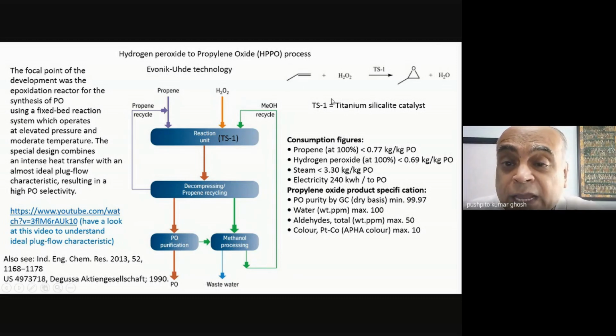And what it is that you take, it's like a zeolite-based catalyst which is loaded with titanium silicalite. Okay, that's what it's called, TS1. And amazingly, TS1 very selectively allows H2O2 to oxidize propylene to form propylene oxide. And obviously, there's nothing better than that because you don't have to form this chlorohydrin and generate calcium chloride. What are you going to do with calcium chloride with all this waste? Whereas look at the elegance of this. I'm just left with water after reacting it.